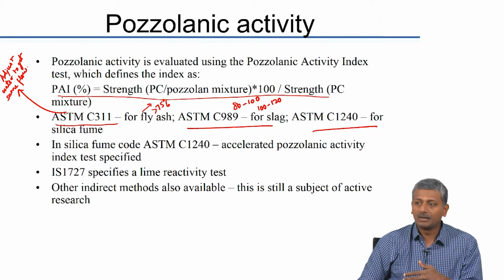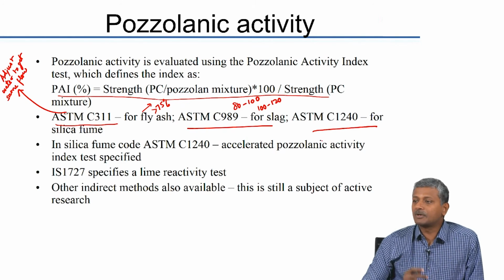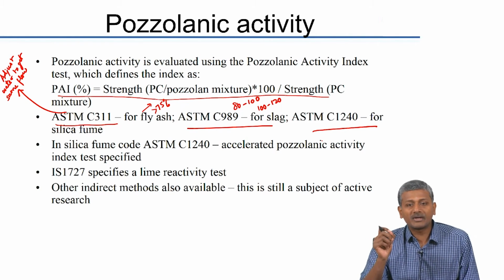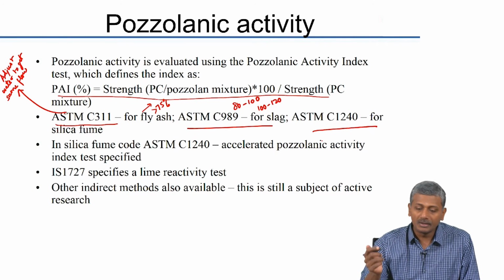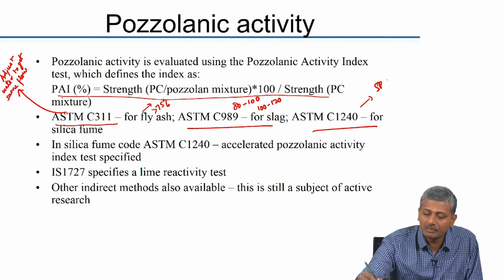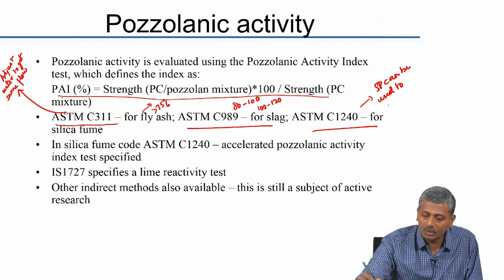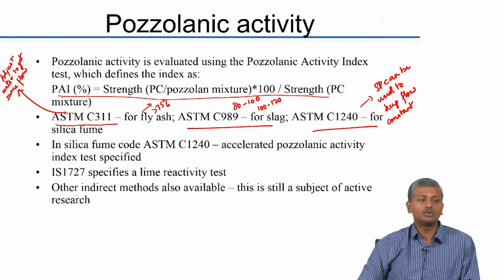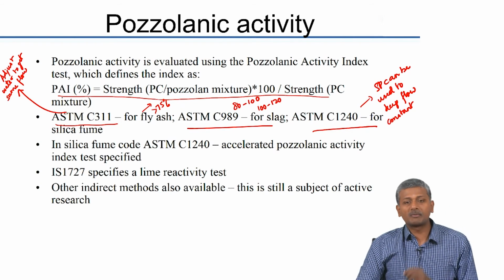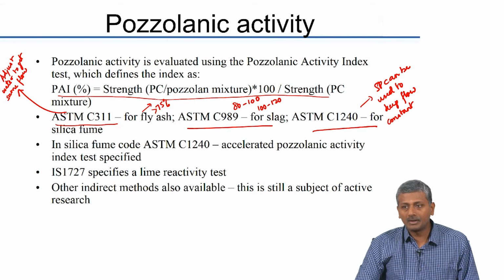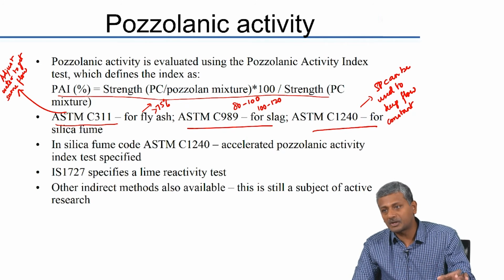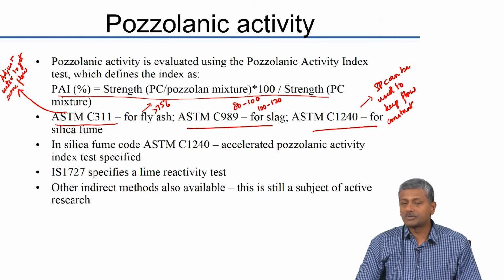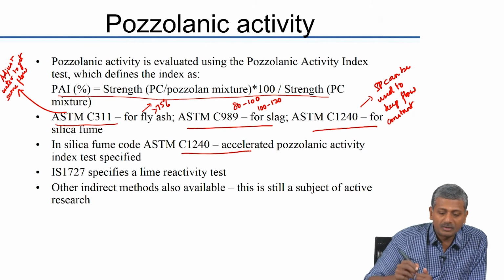With silica fume, you know very well that because of the very fine particle sizes, you may actually end up increasing water demand tremendously. So, here a superplasticizer can be used to keep flow constant. That means you have a constant water to cement ratio or water to binder ratio, and you add a superplasticizer to maintain the same flow. So, you are testing different mineral admixtures with respect to their own categories of pozzolanic activity.